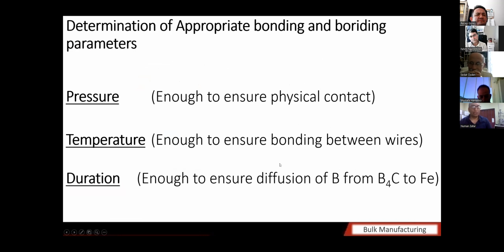I want simultaneous iron boride formation, and I also want the interwire bonding. I need to take care of three parameters, and I will go one by one. Pressure is an important parameter. I need to know what type of pressure I should exert for the wires to be bonded. Temperature, there is nothing much I can do about that, because at least above 900 degrees centigrade is required for the in situ synthesis. And duration also, because diffusion of boron into the iron requires a lot of time. We must have enough time to ensure formation of iron boride phases.